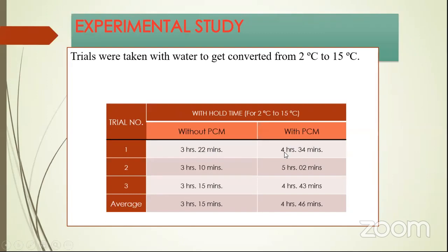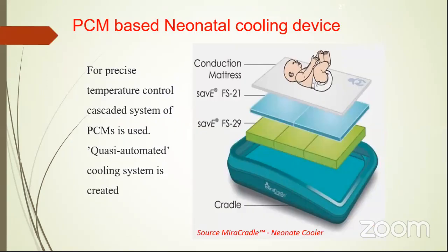With PCM, that holds more than 1 hour longer. So 4 hours 34 minutes, like this; second sample, 3 hours 10 minutes; 5 hours 2 minutes. On average, we have 3 hours 15 minutes without PCM and 4 hours 46 minutes with PCM. So that is the reason why we are choosing PCM, right? And the kind of PCM also is important.